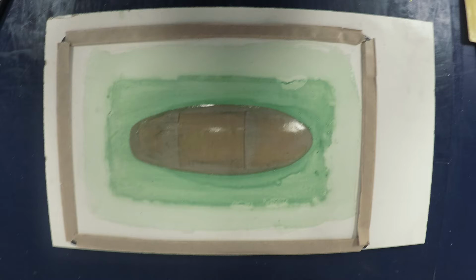The release agent is one of the most crucial things in this process, as it is what allows the cured component to separate from the finished mold surface. This is accomplished by creating a physical barrier with poor adhesion properties for the uncured bonding material or matrix to adhere to. If this step is skipped or rushed, meaning not enough coats or not enough time between coats, it is very likely that the final component will not separate from the mold, and damage or total loss will happen